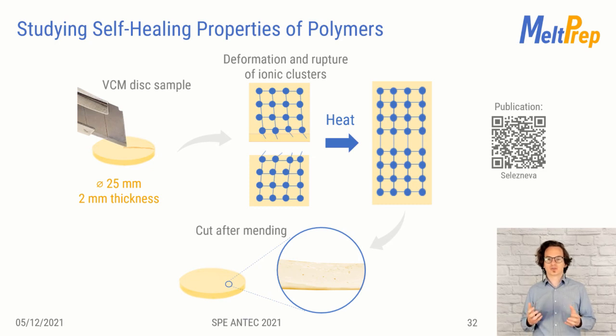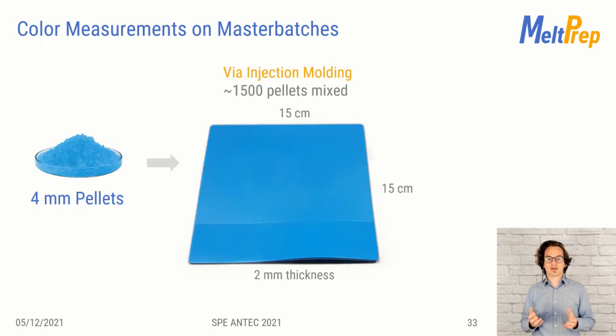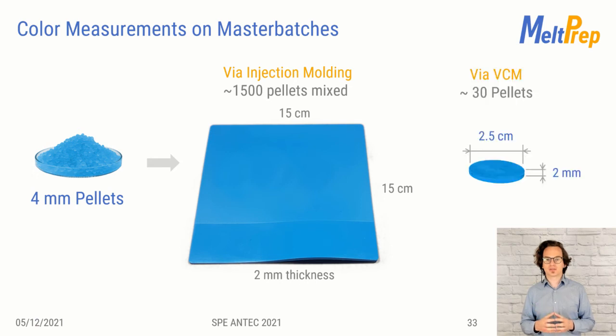Let's move on to a color measurement example. VCM is very valuable when it comes to the measurement of color of master batches. Here we've used blue multicolor pellets via injection molding, first on standard test samples with 15 by 15 centimeters and a thickness of 2 millimeters, and compared it to standard samples produced via VCM with 25 millimeter in diameter.